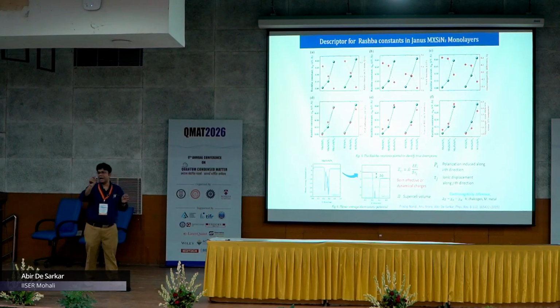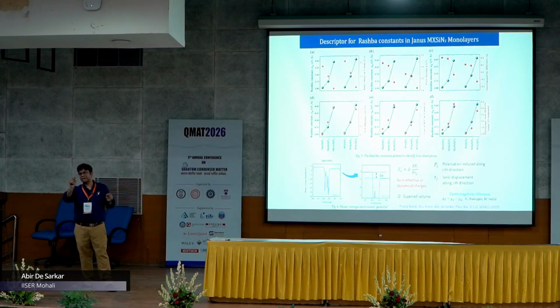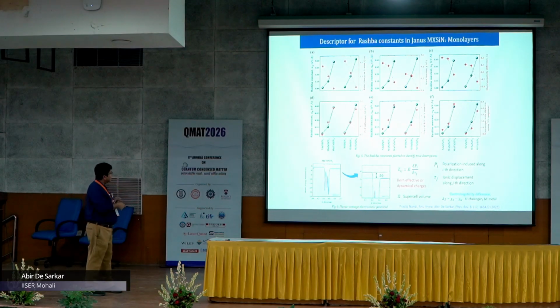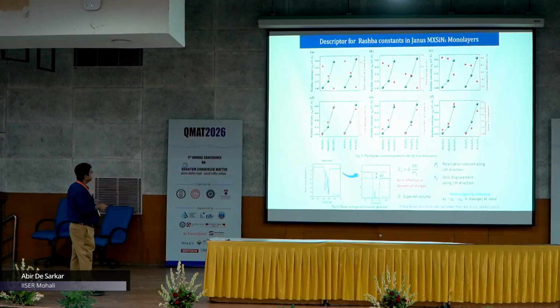So, if you displace an ion along the x direction, polarization can be induced along the x, y and the z direction. So, this is a tensor. So, the Rashba constant is also found to be proportional to the trace of the Born effective charges, and also the macroscopic static dielectric constant. Rashba constant scales inversely with the Bader charges on the chalcogen atom, the work function and the electronegativity difference.